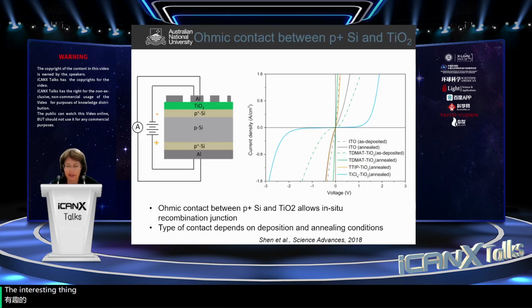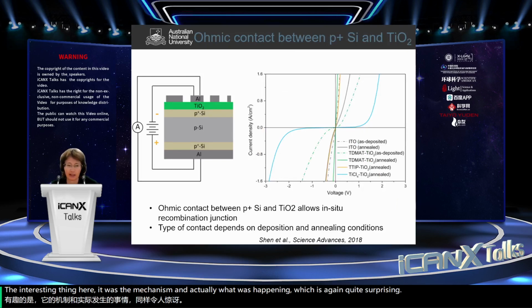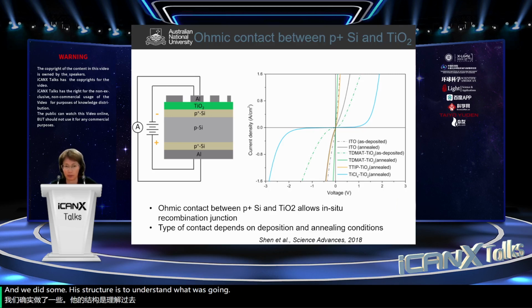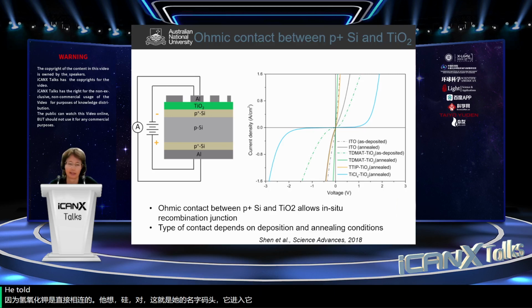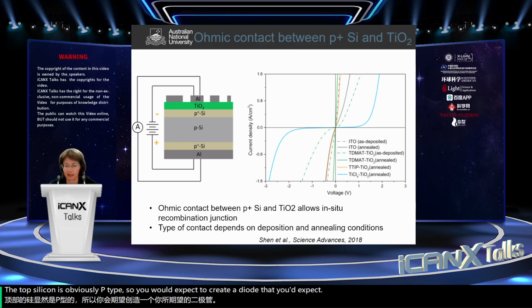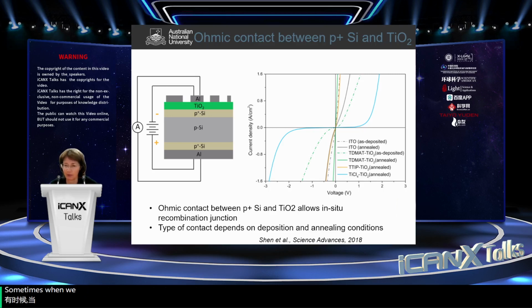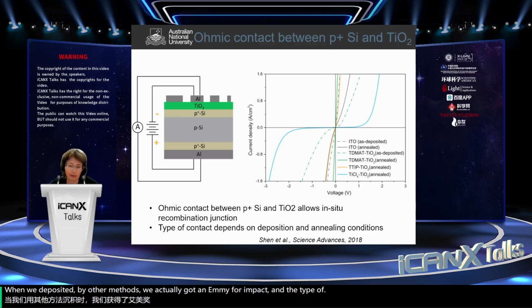The interesting thing here was the mechanism and actually what was happening, which is again quite surprising. We did some test structures to understand what was going on, because what we had was titanium dioxide directly connected to P-type silicon. Now, titanium dioxide is N-type, P-type silicon is obviously P-type. So you would expect to create a diode there. You would expect a Schottky junction. And indeed, we found that was the case sometimes when we deposited titanium dioxide by some methods. But when we deposited by other methods, we actually got an ohmic contact, and the type of contact depended on the deposition and annealing conditions.